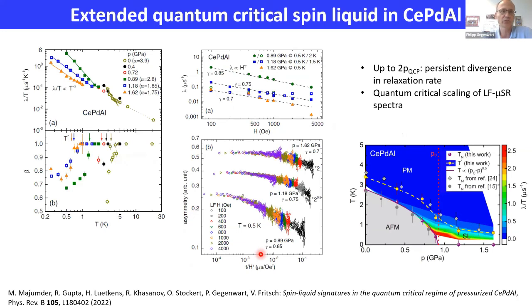And we found in the longitudinal field μSR spectra some interesting time over field scaling, as indicated here, which indeed indicates quantum critical behavior, quantum critical scaling in this pressure range between the first and the second critical pressure. So the idea now here is that we have an extended pressure range where spin liquid correlations remain and where we see quantum criticality. And so